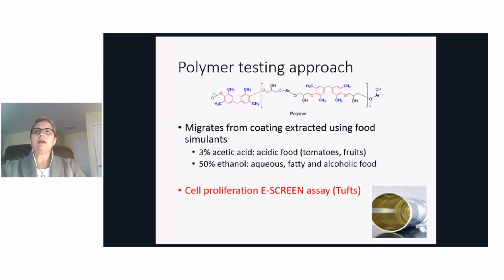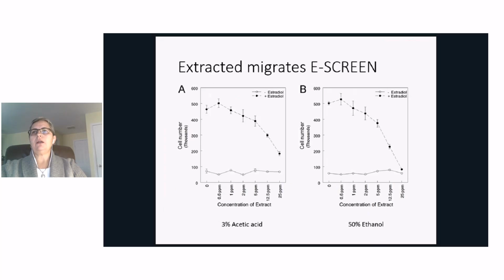So these extracts were then tested in the E-screen assay that, as I said before, is based on whether the cells will proliferate in the presence of a chemical with estrogenic activity. So again, here these are the dose response curves for the 3% acetic acid, and on the right-hand side is for 50% ethanol. As you can see on the bottom, the dose response curves were flat, and there was no increased cell proliferation.